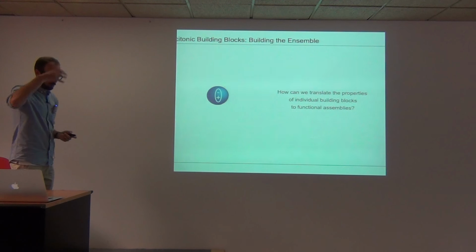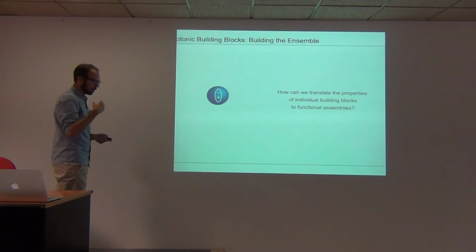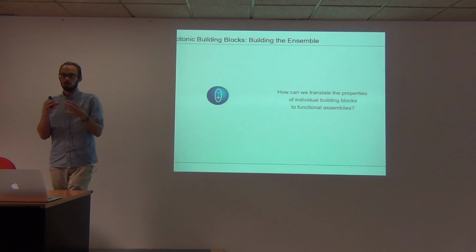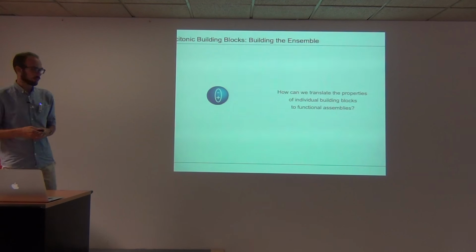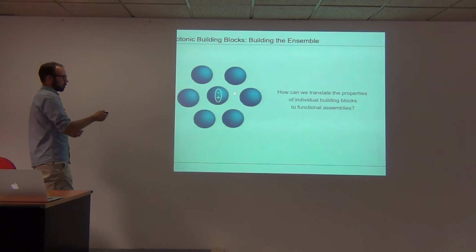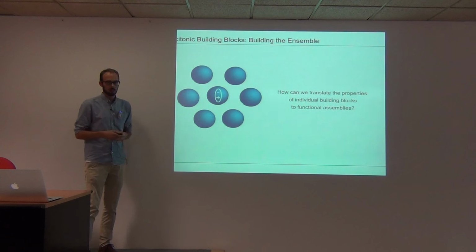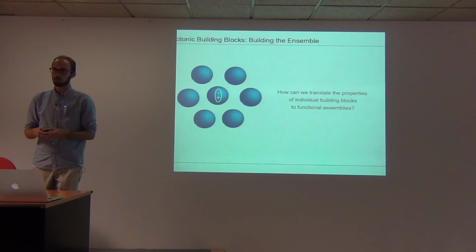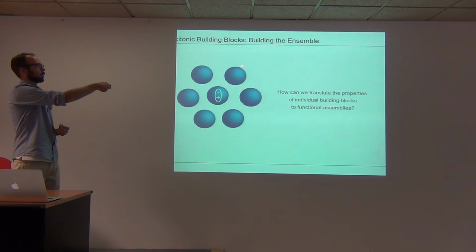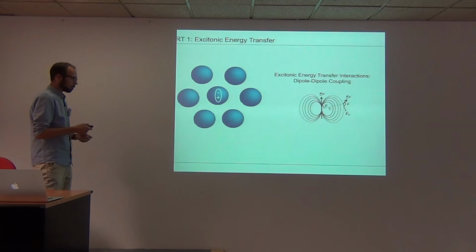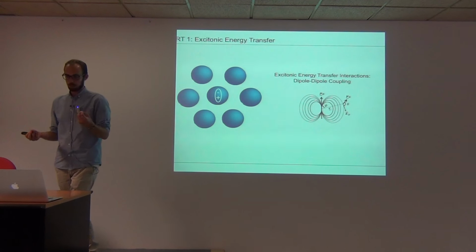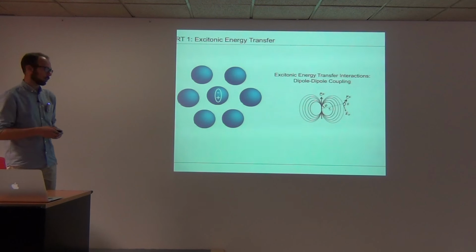There are a lot of studies that have been done on the electronic properties of these nanocrystal films, but what about the excitonic properties? How does the exciton, as a quasi-particle, as a package of excited state energy, behave in these kinds of assemblies? What becomes very relevant if we talk about the excitonic dynamics in these assemblies is the dipole-dipole coupling between, again, these electric field lines that are emitted by this particle and how it couples to its neighbors. So basically, it's a very conventional problem of how to describe energy transfer between donors and acceptors.